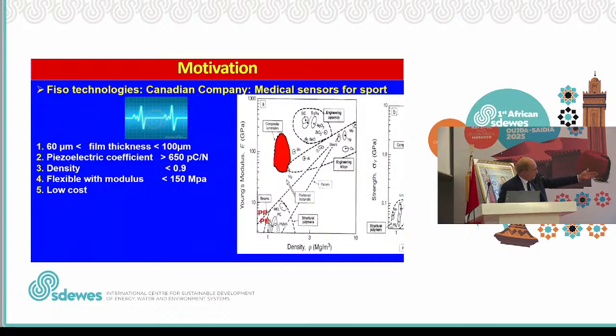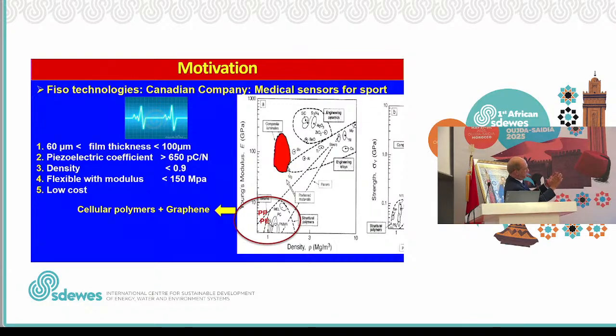So if you look at all known materials, you have polymers, like polyethylene and polypropylene. They have a density which is around 1, which is still good, but it's not what we are looking for. They have a low modulus, a few gigapascals, but we are looking for megapascals, not gigapascals. So we have to reduce the modulus and we have to reduce the density. How to do that? We took, for instance, polypropylene. We generate some cellular structure inside this polymer. If you generate some voids inside the material, then you will decrease the density, and at the same time you increase the deformability, you decrease the modulus.